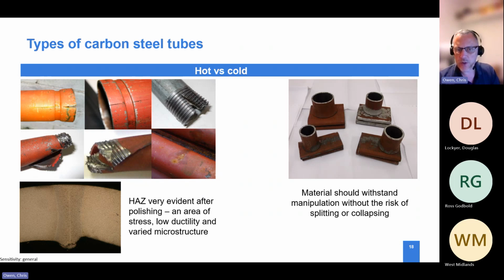And that gives us a tube which can be more readily manipulated without the risk of splitting or collapsing. The images on the left show examples of where tubes have split along that weld line. And on the right, you can see when we have normalized tubes as part of our own in-house testing and validation process, which is above and beyond what the standard asks for, we'll do drift expansion tests and flattening tests.